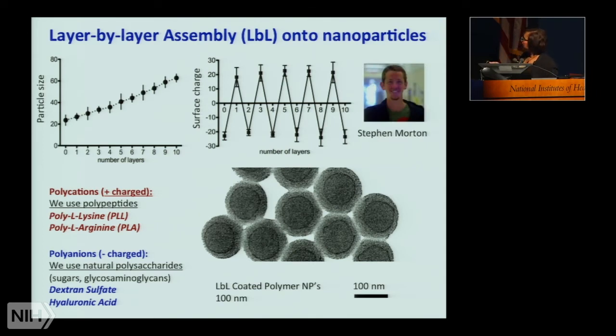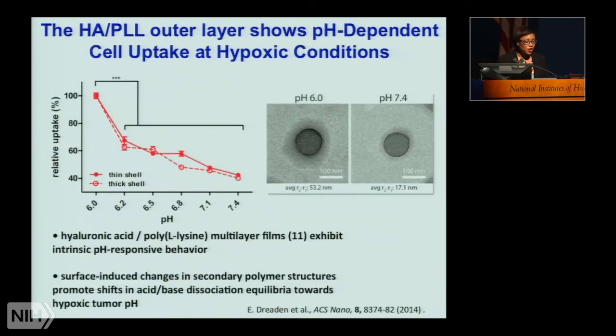And I'm describing some of the work of Stephen Morton, who is a graduate student in my lab. When we began to examine the behavior of these systems, we made several interesting observations. The fact that this is a layer-by-layer film gives us an advantage because we can layer a film which has a very stable nature to it at pH 7.4. However, with hyaluronic acid, it turns out, this particle built at pH 7.4 gives us this strong negative charge, which begins to disappear if we move it to slightly more acidic environments.